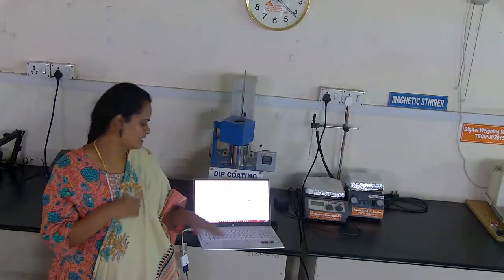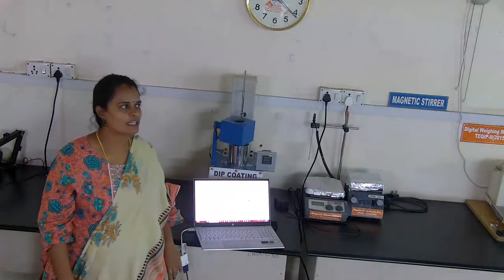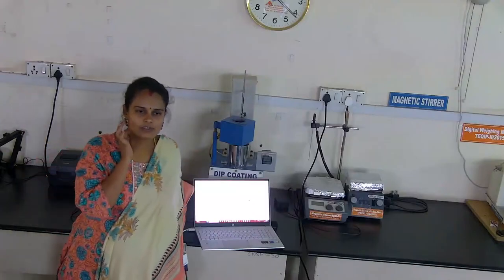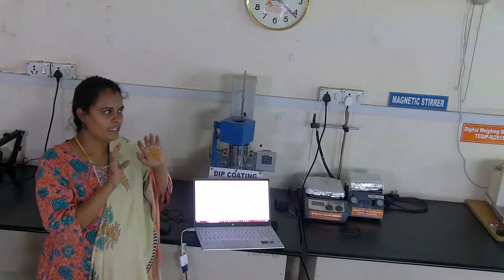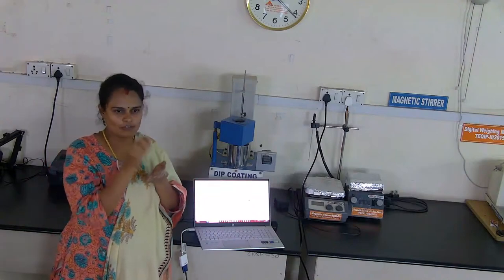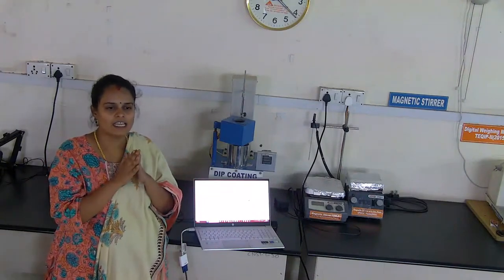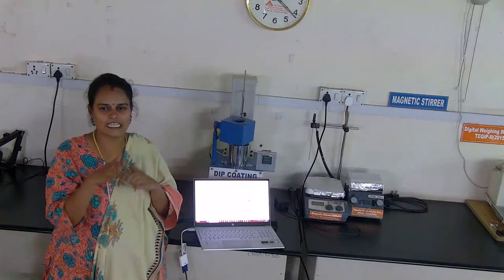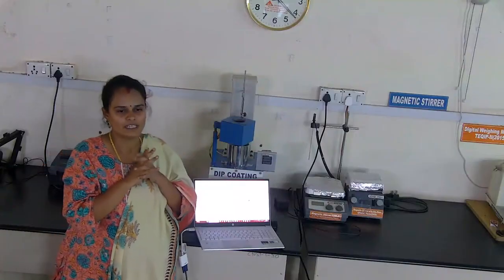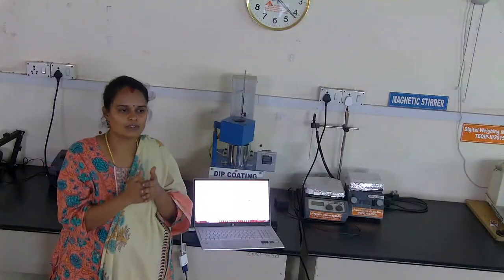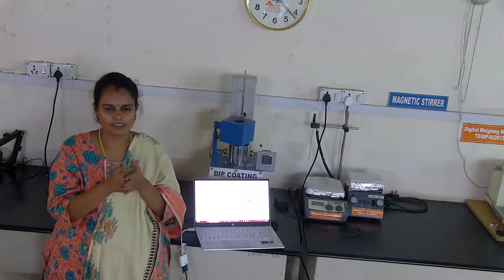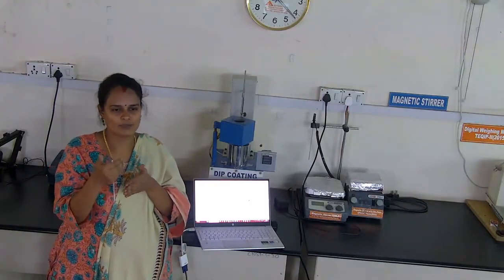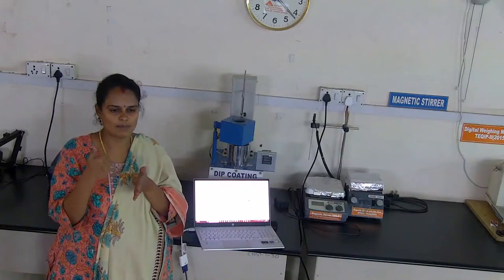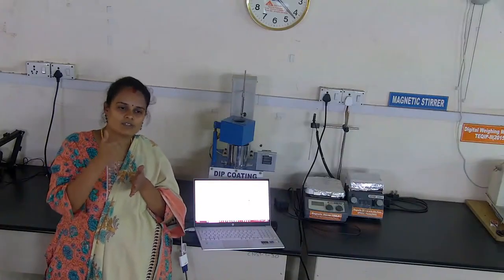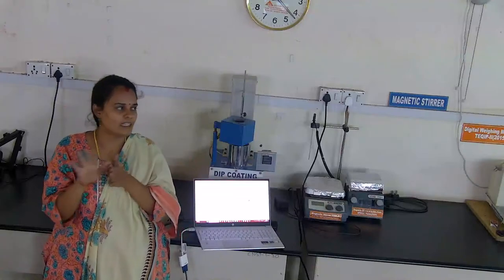So this is the setup actually. I will show you, we have some coated electrodes and bare electrodes. The main concern here is, we will do every experiment based on glucose, we will drop it and we sense the glucose, but we will tell the results as enhancement in the current only. So we can't see anything else. People think they can expect to see glucose sensing. No, we will expect everything in the current variation, the current we are getting only. So for example, if we are getting 10 microamperes current on the bare electrode, after the nanomaterial the current has to be increased because of the electron transfer capabilities and all. After adding the glucose, the current has to be more than the bare electrode. So that is what mainly we need to check.